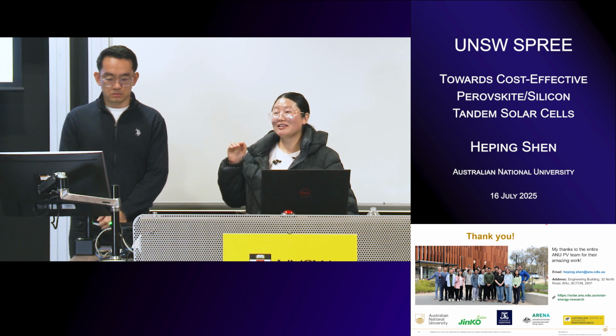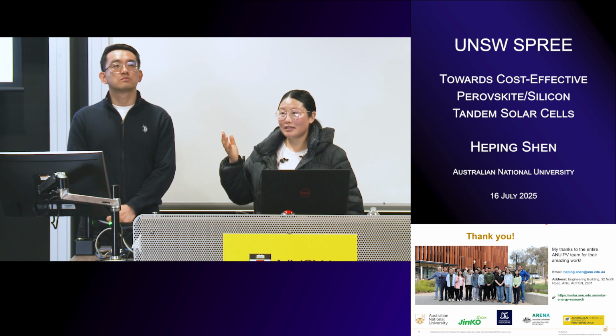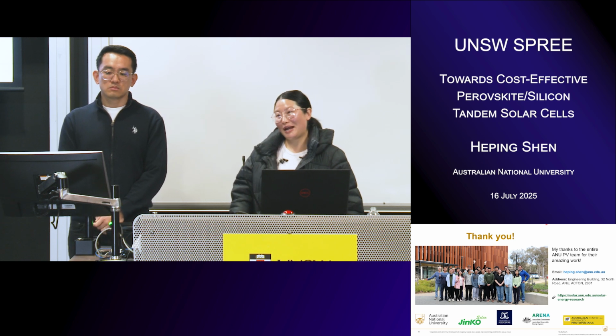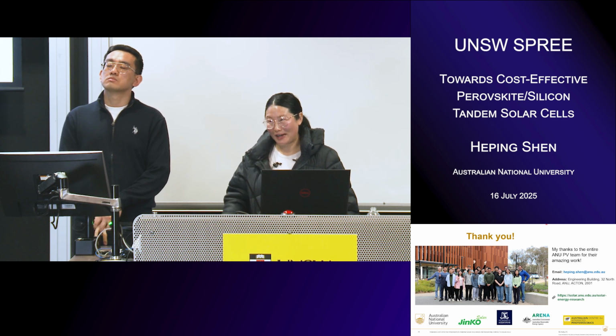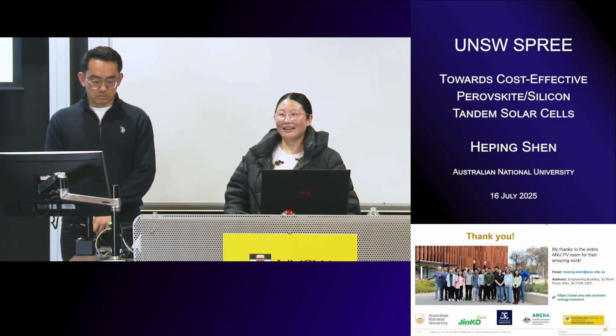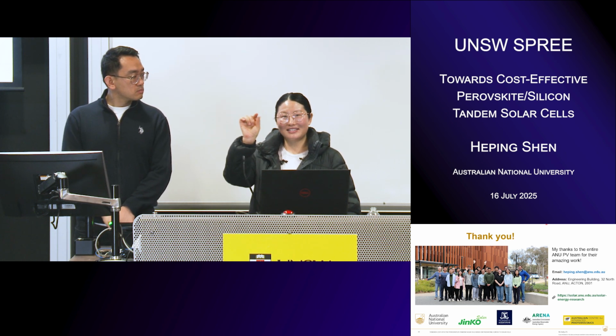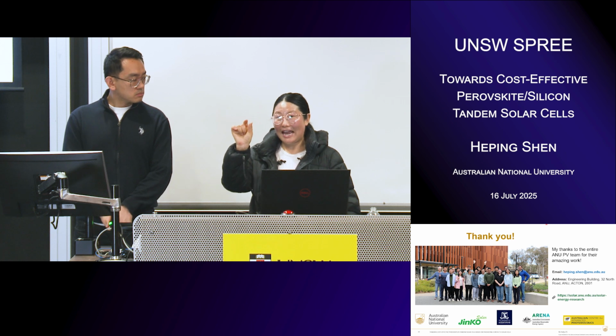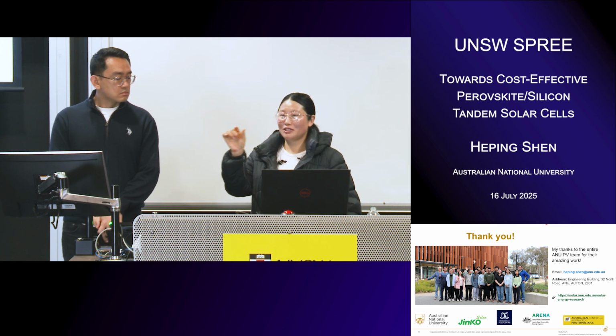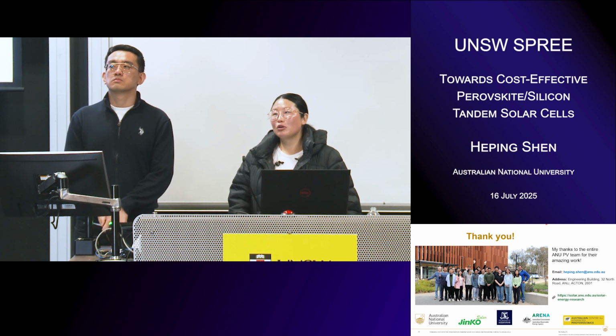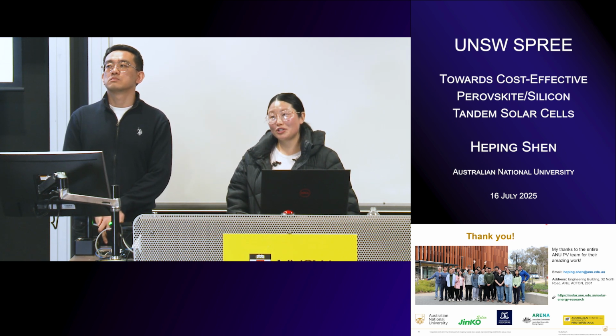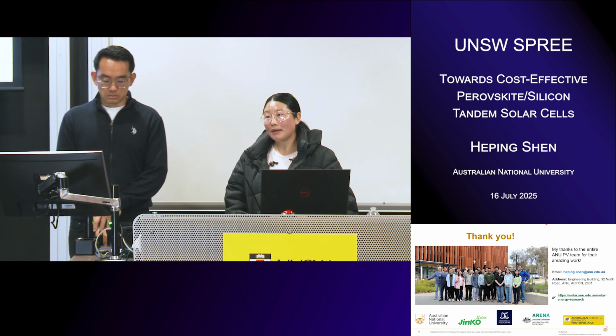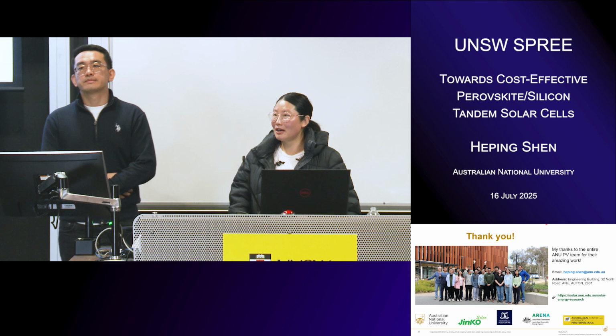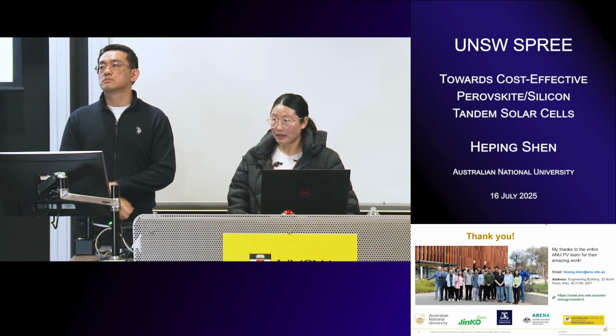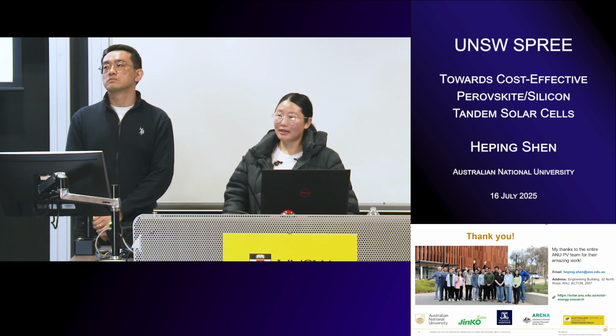I think another challenge is that, yes, some self-assembly materials are very nice in terms of pursuing high efficiency, reporting record efficiencies, but in terms of upscaling, it will be very challenging. Assuming a SAM layer which is only one molecule thick at hundreds of square centimeters, a few square meters, I reckon that will be a significant challenge, which also is what we see in our lab. So we always think it's very important to have an inorganic layer there to allow the upscaling, maybe with the assistance of this SAM, but probably not solely with the SAM.